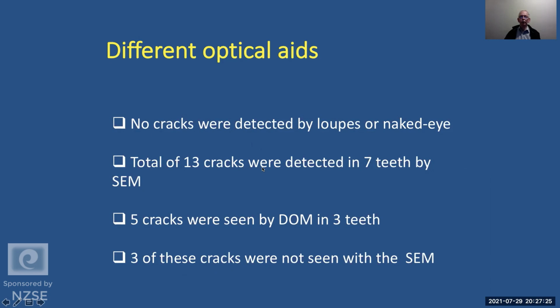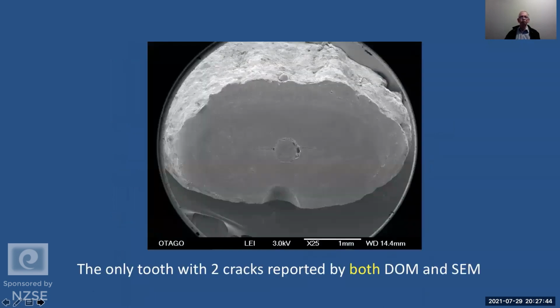13 cracks were found in 7 teeth with the scanning electron microscope. 5 cracks were seen with the microscope in 3 teeth, and 3 of those cracks were not seen with the SEM. So in other words, we're looking down the microscope saying the tooth's got a crack in it, and when we get the scanning electron microscope picture, it doesn't seem to have one.